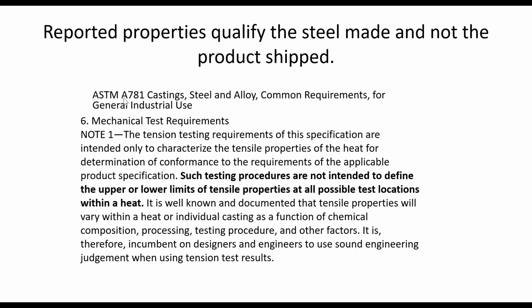All of the steel casting grades are referred to either ASTM A703 for pressure containing, more critical parts, or A781 for general use. And you can see we have basically the same note in the ASTM casting standard that they do in the plate and bar standards. The tension test requirements are intended only to characterize the tensile properties of the heat for determination of conformance to the requirements of the specification. They're not intended to tell you all the tensile properties everywhere.